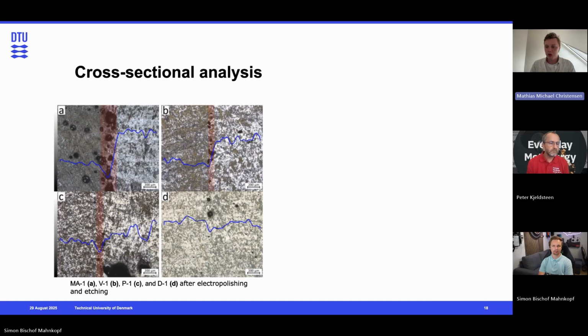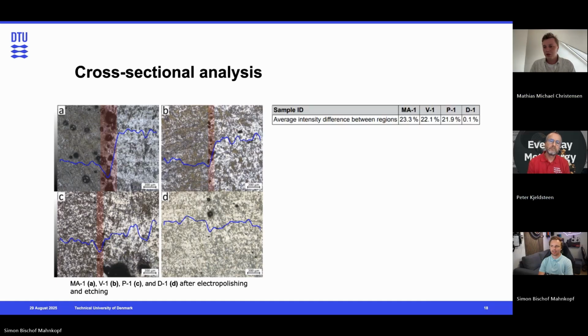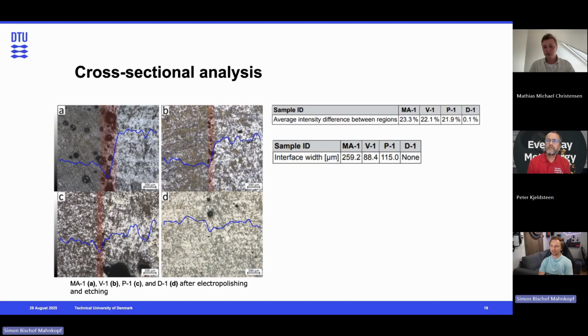And so that's what we also looked at. Yeah, so if you look here, we have the interface we detected. You can see that the old sample was really dependent on the porosities in the detected interface, because we used the grayscale, and porosities are black or very dark in the images. But when looking at just the microscopy images, the micrographs, you can see that the porosities in the interface look lower for samples B, C, and D than sample A. There's a significant amount of porosities in sample A.